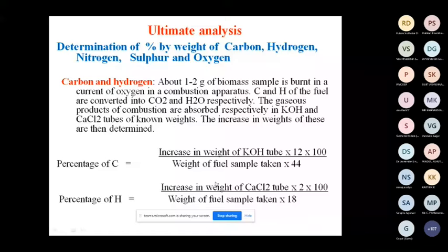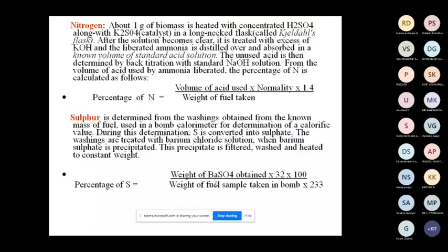Then nitrogen is a very old technique by Kjeldahl flask. You take about 1 gram of biomass sample, heat in sulfuric acid along with potassium sulfate catalyst. Then heated. After this, excess sodium hydroxide liberates ammonia. The liberated ammonia is treated with acid. Again, the balance acid is treated with standard sodium hydroxide. So from the ammonia you can calculate the percentage of nitrogen, which is equal to the volume of acid used into normality into 1.4 divided by weight of the fuel taken. So using this Kjeldahl flask, you can measure the nitrogen content of the biomass fuel.